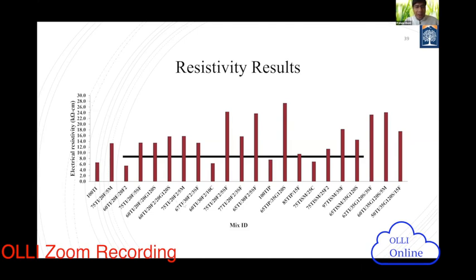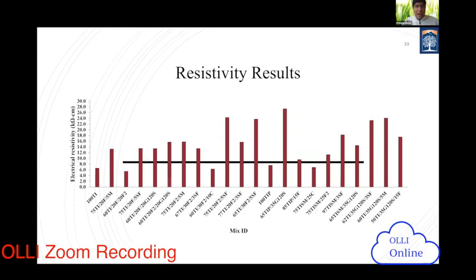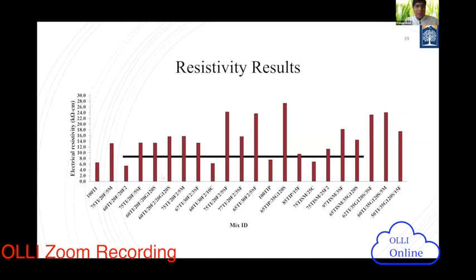These are binary and ternary mixtures basically, so either two-component or three-component. The first one is only 100% Portland cement. So you can imagine that most of the binary and ternary mixtures provide a benefit compared to your 100% Portland cement mixture. So these are the initial data. We have tested more data later, but I just wanted to show some initial data. So that is the beneficial effect.